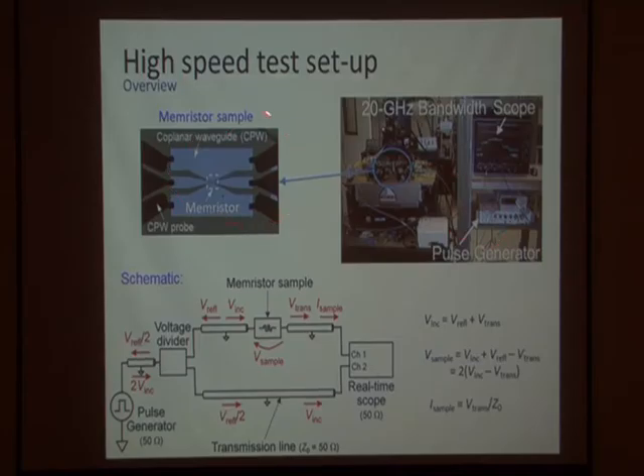They designed the structure, and this is a coplanar waveguide structure. Why coplanar? Because here's the center conductor, and this is the other boundary condition, if you will, of your waveguide. If you're talking about a 20 gigahertz or a 30, let's just make it 30 to make it easier, you're getting a wavelength of about 1 centimeter, and you're trying to squeeze that into a few microns, like a 2 micron by 2 micron device. So what's going to happen? It's going to reflect.